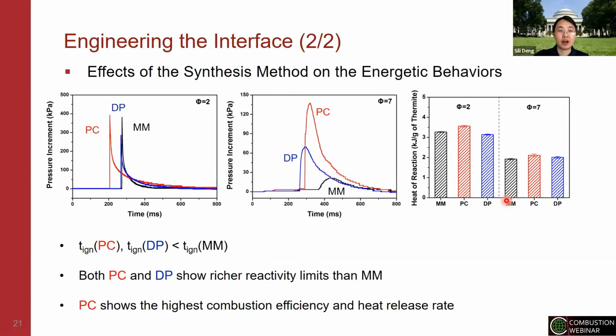And again, we are characterizing the performance in the constant volume combustion chamber, as well as in the bomb calorimetry. And the take-home message is indeed with some more advanced synthesis method compared to the traditional method, the ignition property as well as the flammability actually all gets improved if we are using the more advanced precipitation or the displacement method. And also the heat release gets improved, meaning that the combustion efficiency gets enhanced with a novel synthesis method.